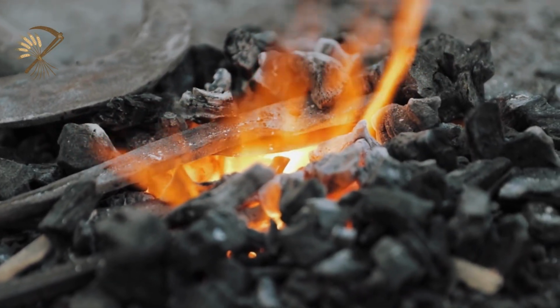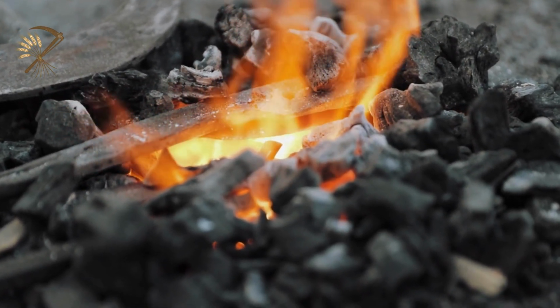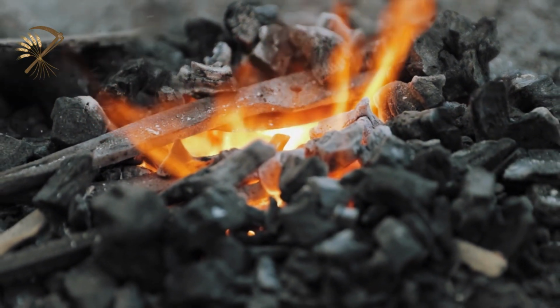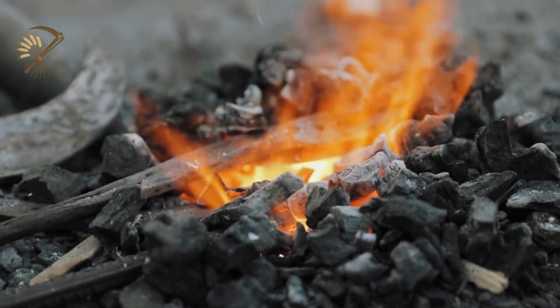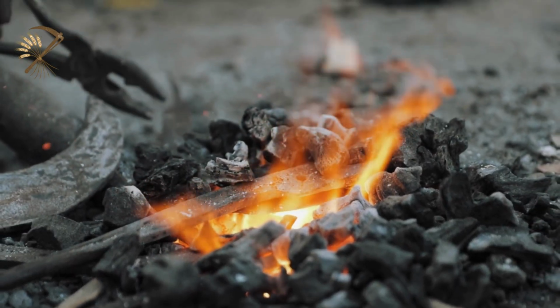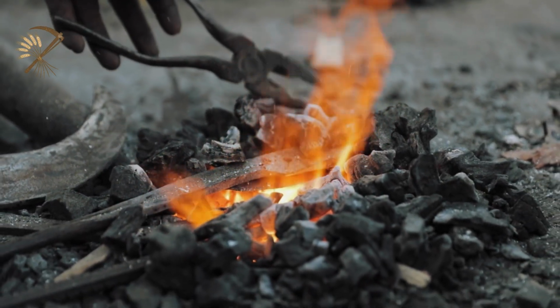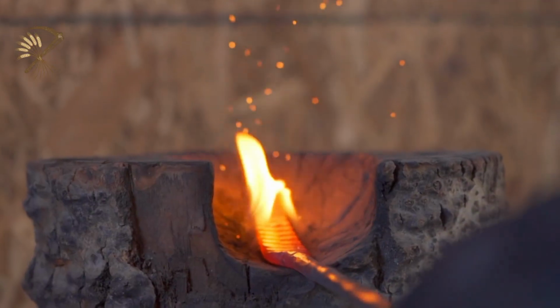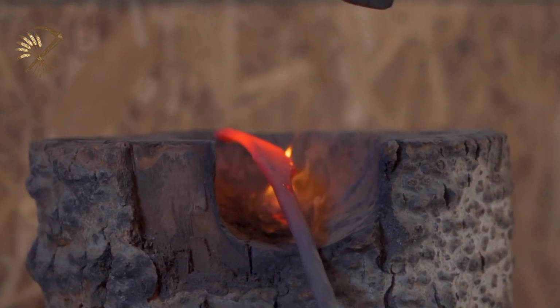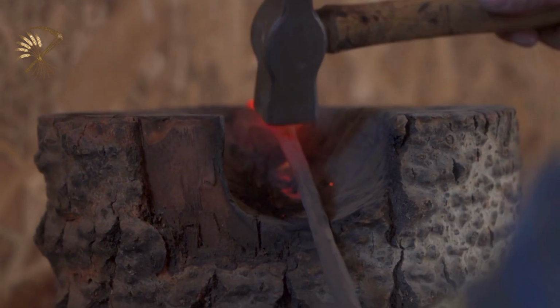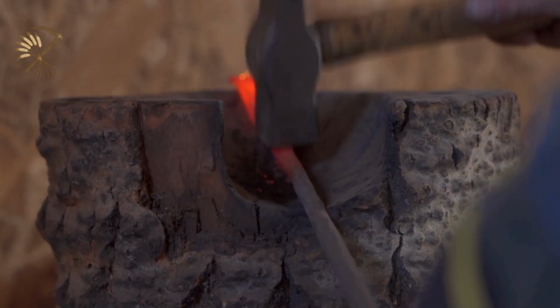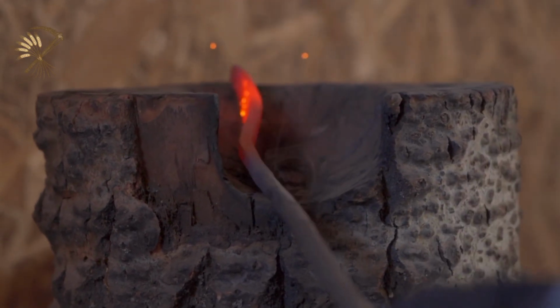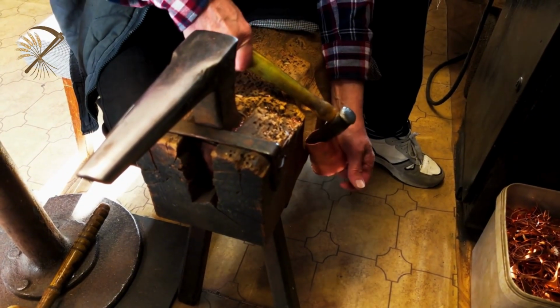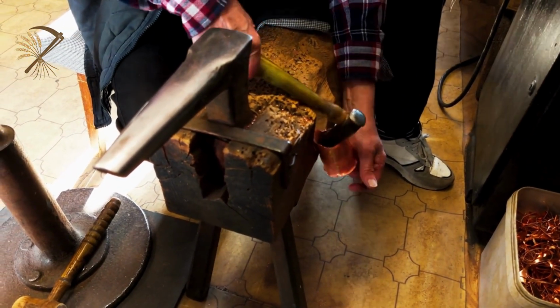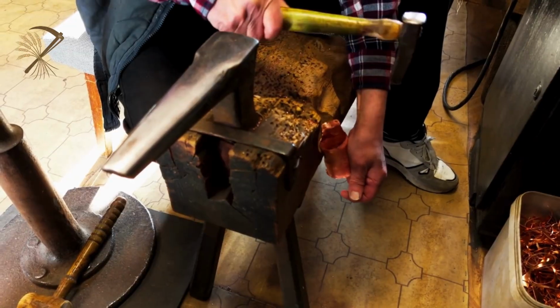Coal forges are traditional and preferred by most Amish smiths because coal burns hotter and longer than propane, costs less per BTU, and provides the reducing atmosphere that prevents excessive oxidation of heated steel. A coal forge consumes 20 to 30 pounds of coal daily during active work, costing $3 to $5 daily or $60 to $100 monthly. The bellows or blower forces air through the fire, increasing combustion intensity and temperature.